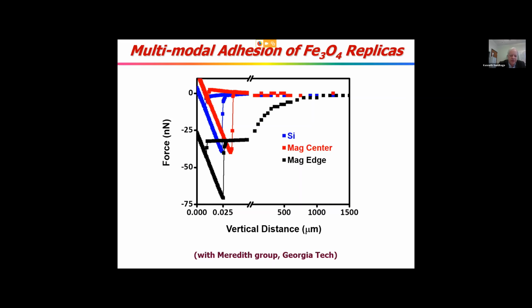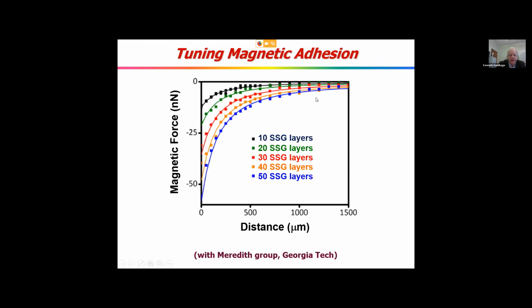But if you put the pollen particle on the cantilever on the edge of the permanent magnet where the field is much stronger, not only do you get the short range adhesion, but you also get long range adhesion due to the magnetic nature of the replica, out to about 1 millimeter. And in fact, of course, if you put more of the magnetite on by having thicker layers, you get more of a long-range effect as well in terms of the force applied.